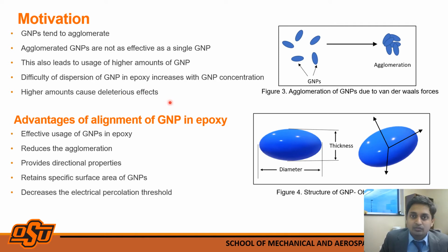One of the reasonable solutions to remove agglomeration of graphene nanoplatelets is alignment. Alignment of graphene nanoplatelets will not only utilize the directional properties but also retain the surface area of graphene nanoplatelets, and it also decreases the electrical percolation threshold, which is suitable for electrical applications. The structure of a graphene nanoplatelet is an oblate spheroid, as seen in figure 4, which makes it very suitable for alignment in the parallel direction.